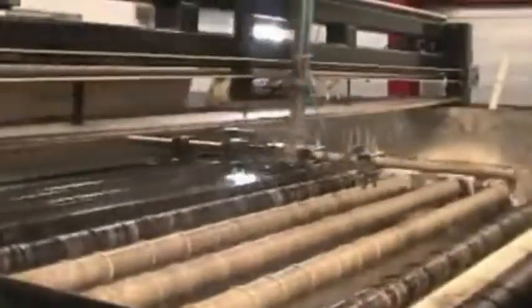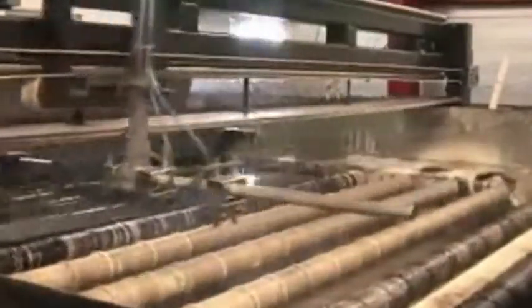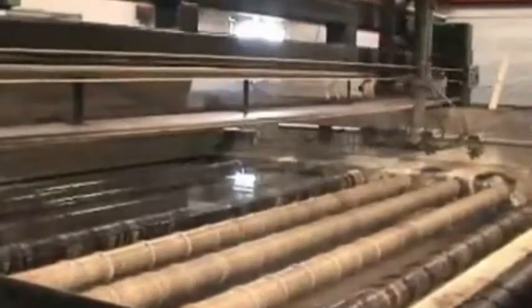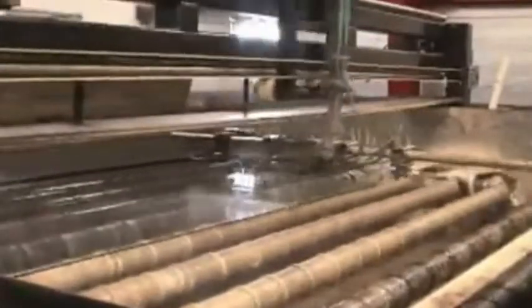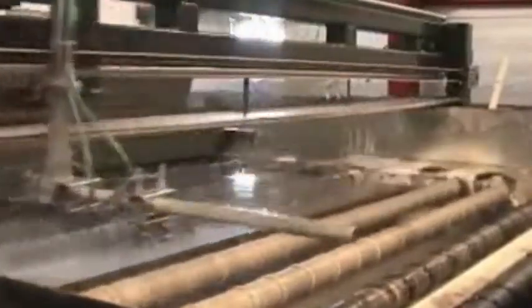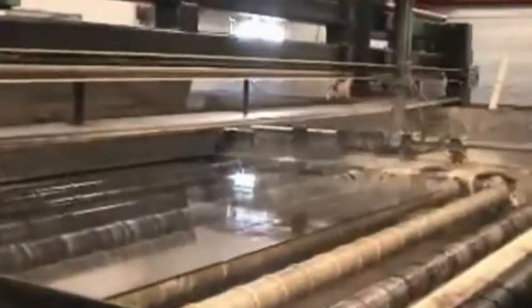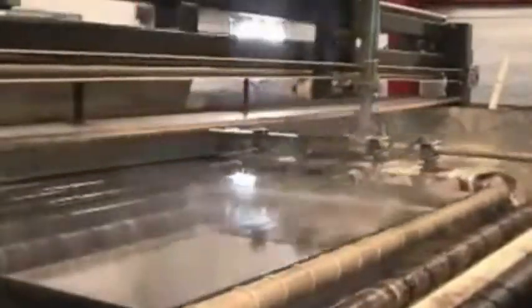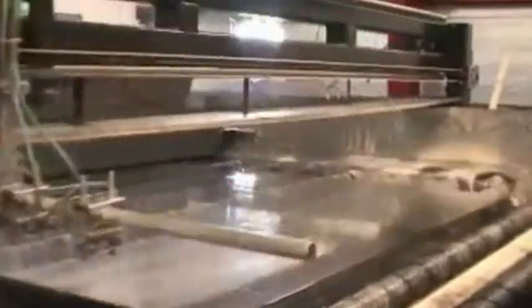The deionized water rinses the glass at an average of 40 psi, and water temperatures are adjusted to achieve a glass temperature between 80 and 90 degrees Fahrenheit, which is optimal for the tinning section of the process. In the tinning process, the tin solution is sprayed onto the back surface of the glass. Since silver will not adhere directly to glass, this ultra-thin layer of tin will stick to the glass and provide a material for the silver to adhere.